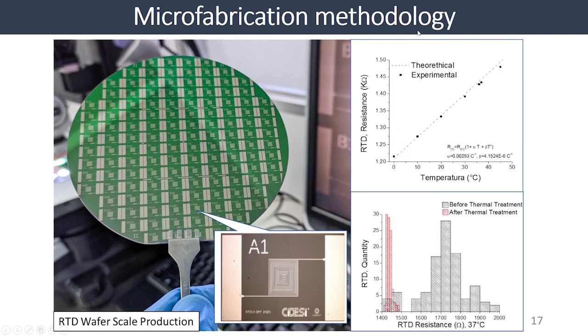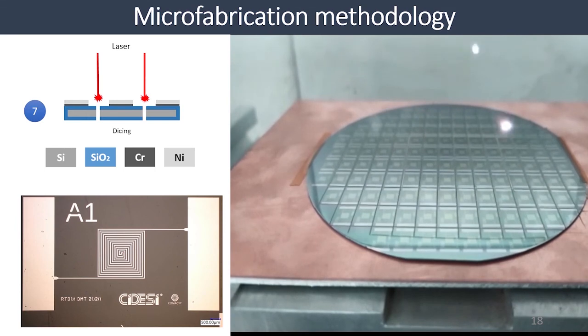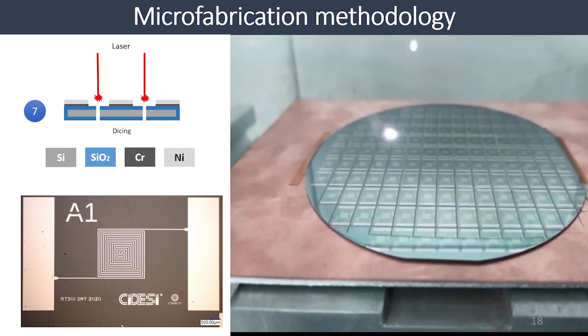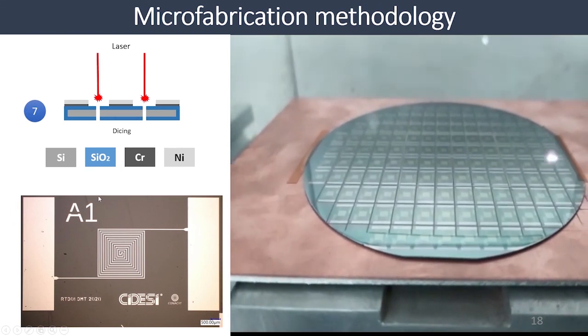And here we can see a graph that compares the theoretical values given by the Callendar-Van Dusen equation and the experimental values that we had. And as you can see, they really match. They are really correlated. Also, we show the experimental thermal coefficients that we had, and they also match the coefficients of nickel. In the second graph, we see the distribution of the resistance values of each of the RTDs before the thermal treatment and after the thermal treatment. As you can see, after the thermal treatment, all the values are really close to each other. At the end, each wafer has to be divided into units, so we use laser dicing. Here is a micrograph of a real final RTD.